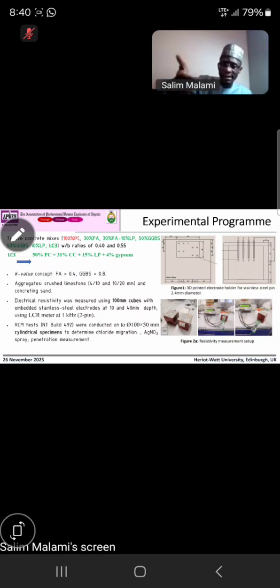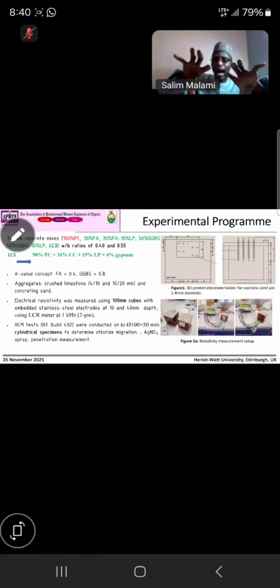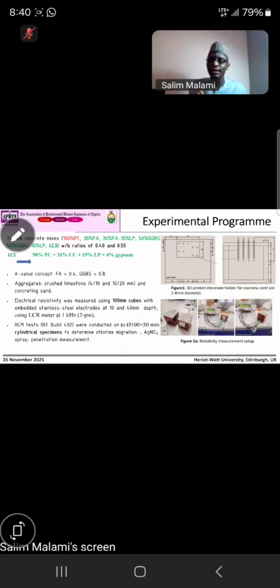Test the electrical resistivity. If the concrete has higher resistivity, this means it can resist the amount of chloride that will pass through the concrete. So the higher the resistivity, the more durable the concrete, and the less corrosion will happen to the concrete. So this is the essence of measuring electrical resistivity.